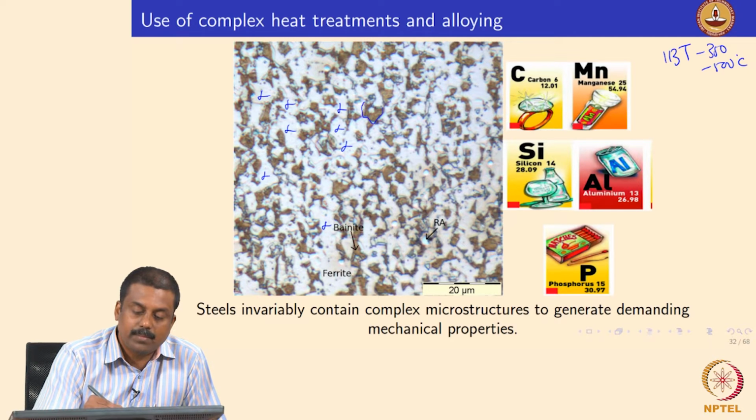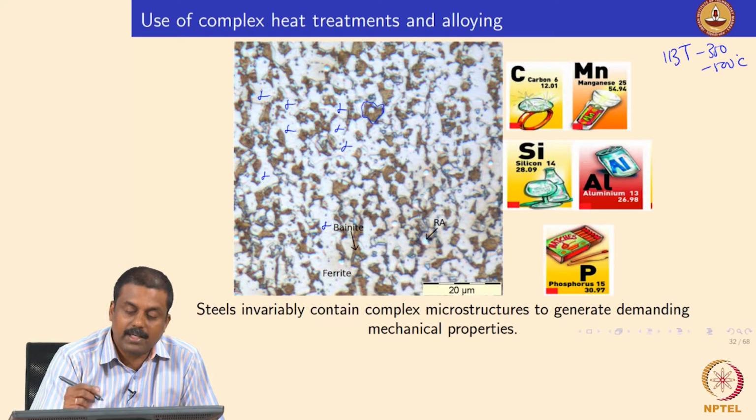Say, for example, this was a prior austenite grain boundary. It will transform some of this austenite into bainitic ferrite, and during this process we push the carbon atoms into untransformed austenite. Upon sufficient carbon enrichment the bainitic transformation ceases. The carbon concentration of this austenite is so high that upon subsequent cooling to room temperature it cannot transform to martensite, because the Mf temperature is lower than room temperature, and so this austenite is retained. Now this microstructure contains 3 phases, right.